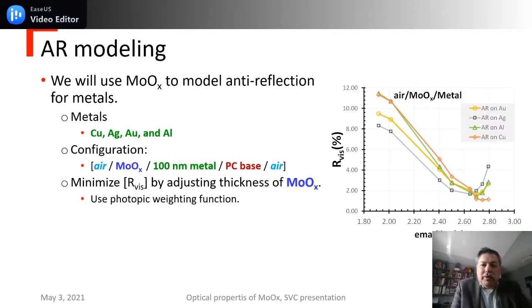Well, we are now ready to start making anti-reflection calculations where we will investigate different metals including copper, silver, gold, and aluminum, where we put a thin film of molybdenum oxide on a 100 nanometer thick layer of the metal, which is on a polycarbonate base. In fact, you can use any base you want, so I'm just using polycarbonate, where this whole thing is embedded in air. When we minimize the reflection, it's really the visible reflection that we are minimizing, where we use the photopic response as a weighting function of the eye. So we're using the eye's behavior to weight the reflection, and we adjust the thickness of the molybdenum oxide layer to discover what the reflection minimum is.